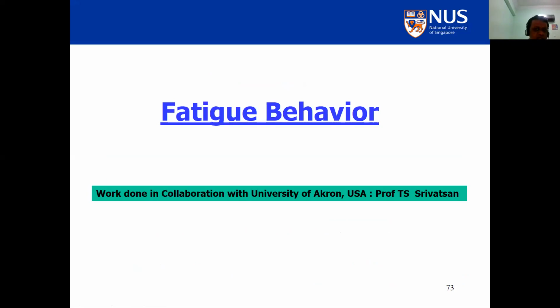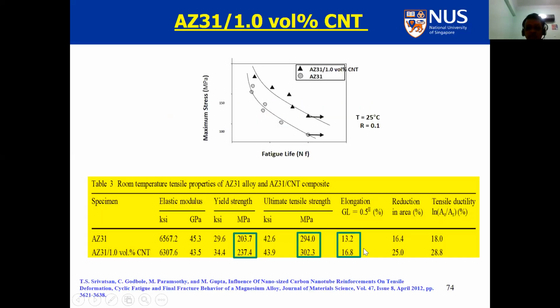Tensile and compressive uniaxial properties are important, but so is the cyclic behavior of the material. That is work we did in collaboration with the University of Akron with Professor T.S. Srivatsan. In this case, we used a commercial AZ31 magnesium alloy, and we put in CNT, carbon nanotube. And now you see, as expected, the yield strength goes up, 203 to 237. UTS goes up, 294 to 302. Ductility goes up, 13.2 to 16.8. So pure magnesium results are reflected by the commercial alloys.